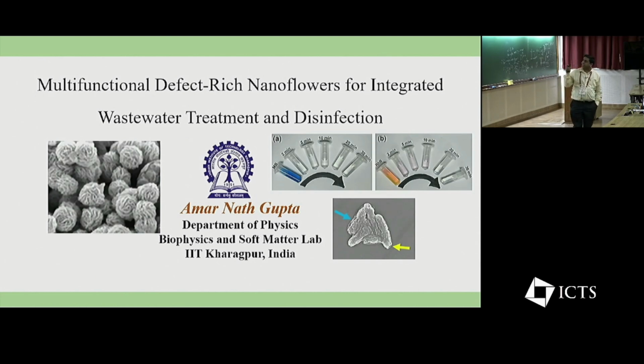And the second application, I'm going to discuss, is the medical application of this nanoflower. If you mix this nanoflower with some bacteria, I have shown here only one kind of bacteria, say E. coli, then this nanoflower interacts with the surface of the bacteria and tries to dent or puncture the membrane, and the cytoplasm will come out, and eventually the bacteria dies.